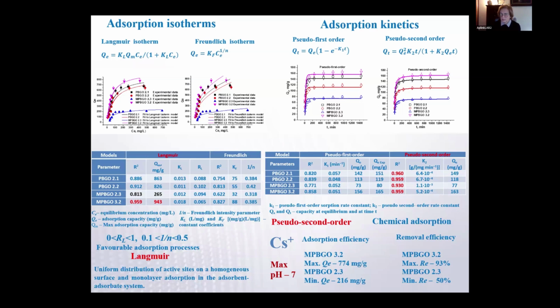Kinetic studies showed that pseudo-second order modeling agreed better with the experimental data, and removal efficiency was really very high for these samples at pH 7.